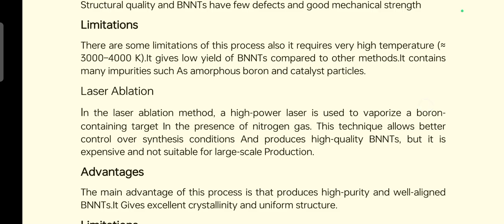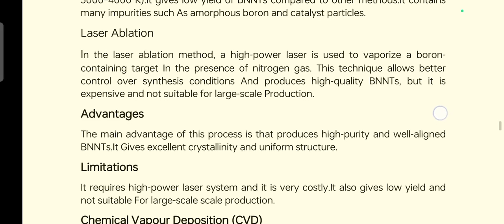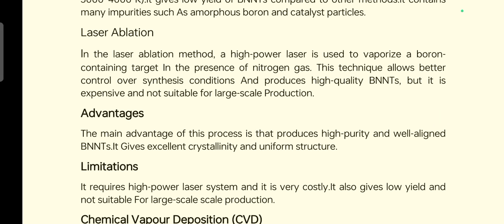Then we will discuss the laser ablation method. In the laser ablation method, a high powered laser is used to vaporize a boron containing target in the presence of nitrogen gas. This technique allows better control over synthesis conditions and produces high quality boron nitride nanotubes, but it is expensive and not suitable for large scale production. Then we will discuss the advantages, as all the processes have some advantages as well as some disadvantages. The main advantage of this process is that it produces high purity and well aligned boron nitride nanotubes. It gives excellent crystallinity and uniform structure.